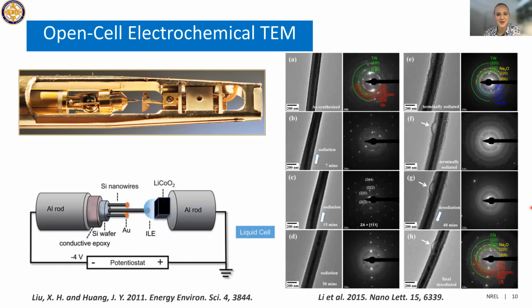Now, I just want to bring up a couple different things that we can do. So a lot of electrochemical testing in the TEM has previously been done using an open cell platform. So this is known as an STM TEM holder because there's a probe on this end here, which then can orient the sample to provide electrical contact. And this has been used for both solid and liquid electrolytes, where you can have your material set up on one side and then come in with either lithium metal with a solid electrolyte on top or with an ionic liquid electrolyte to contact a material, and then watch the material as it cycles.